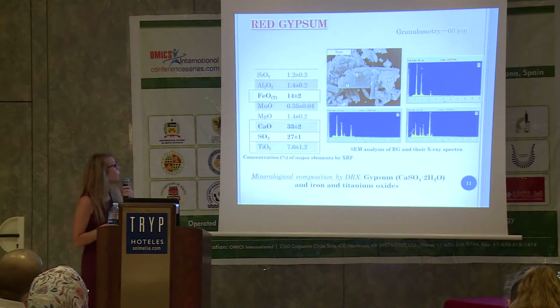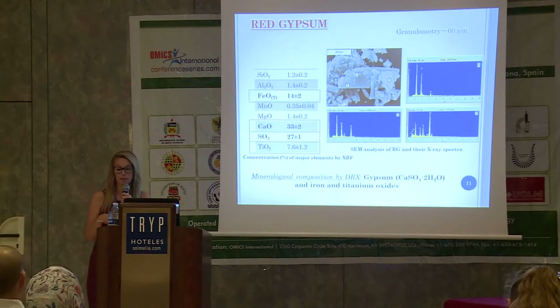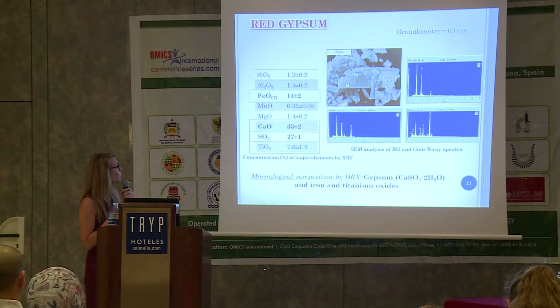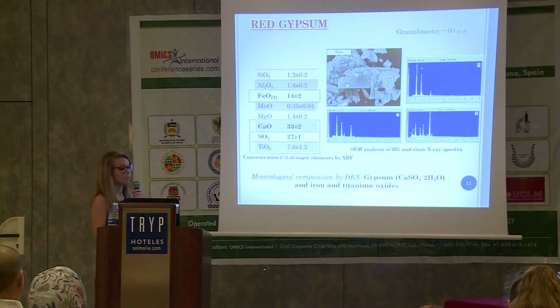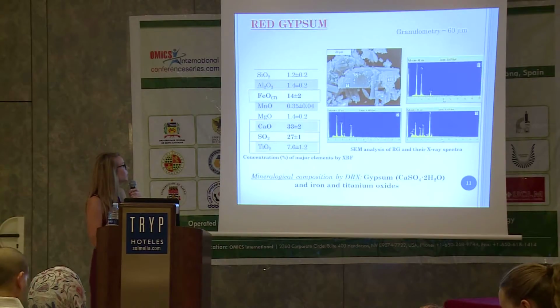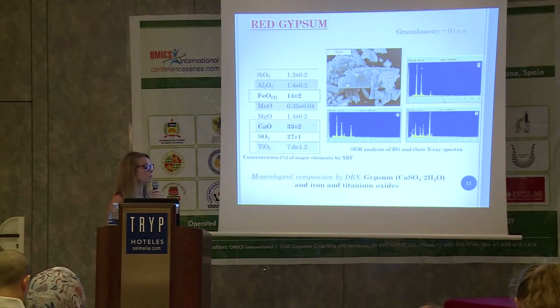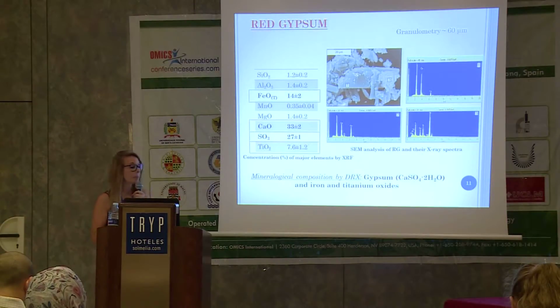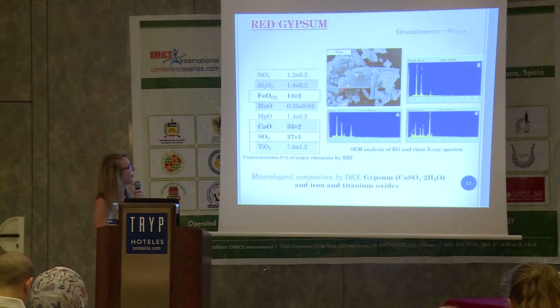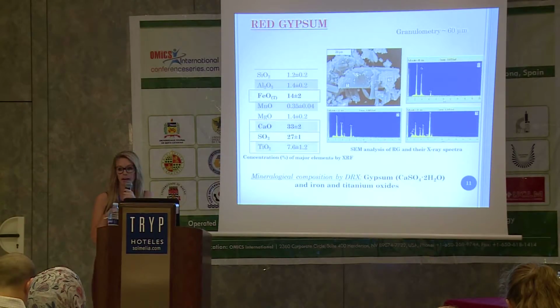Red gypsum is generated in the neutralization of the weak acid stream with calcium hydroxide, and it is composed mainly of calcium, and sulfur, iron, and titanium. According to mineralogical composition, it is composed of gypsum and iron and titanium oxide. In this picture, you can see the characteristic morphology of gypsum, and number 3 is the amorphous phase with high content of titanium and iron.